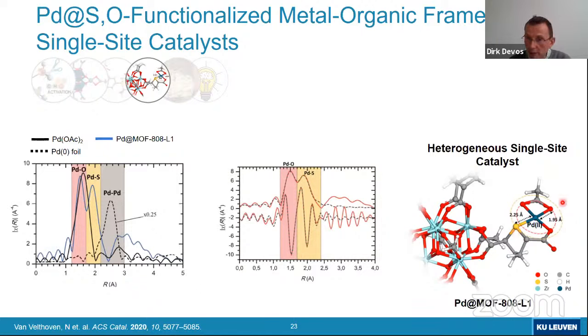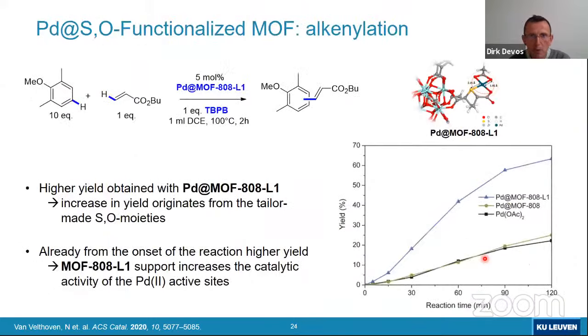And that there is also still an acetate ligand, that's the other ligand that's in the resting state still available on the palladium if you do the loading of this MOF material with palladium acetate. We can also exclude, for instance, that there would be palladium 0 clusters because the typical binding distances that you would have in a palladium foil are just not there when you have the palladium 2 loaded on this ligand-modified MOF-808. Okay.